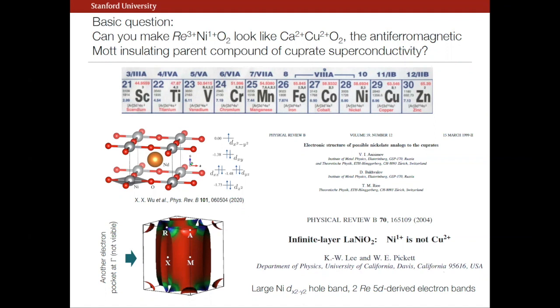And I take here the LDA band structure that he calculates. And in the last 6 months, there's been many more, but at least in the LDA limit, I think there's strong consensus that the electronic structure is primarily a large hole-like, cuprate-like Fermi surface, dx² minus y² character, and 2 electron pockets. There's another one hidden behind this here that arises from hybridization with the rare earth 5D states and the